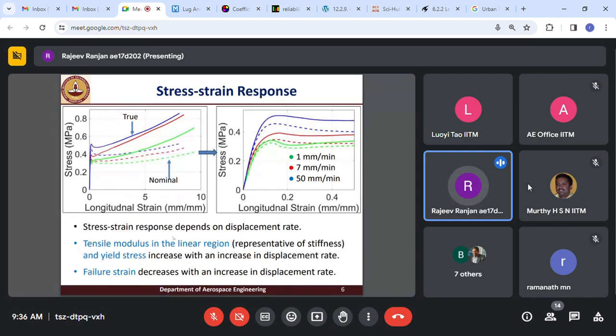Here, the first plot indicates the stress strain response up to the failure of the material, and this plot is just a zoomed in view of this stress strain response up to the failure. This plot is up to 50% strain to see the initial behavior of the material. It was observed that the stress strain response was non-linear, and it was depending on displacement rate. Tensile modulus and yield stress were increasing with increasing displacement rate.